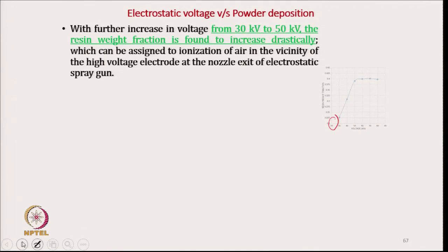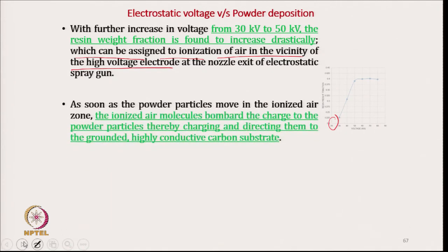With further increase of voltage from 30 to 50 kilovolt, the resin weight fraction is found to increase drastically, which can be assigned to ionization of air in the vicinity of the high voltage electrode at the nozzle exit point, and that helps in the attraction of the particles by the carbon tow. As soon as the powder particles move in the ionized air zone, the ionized air molecules bombard the charge to the powder particles, thereby charging them and directing them to the grounded, highly conductive carbon tow. So, that will automatically be deposited on the carbon tow.